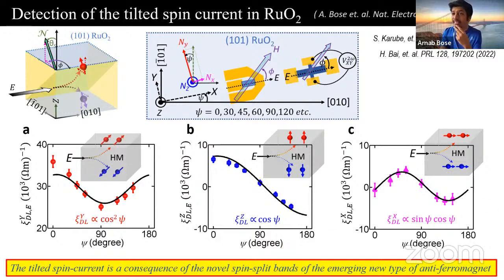We have also seen a couple of recent reports studying spin torques in this ruthenium dioxide, and particularly in this paper, they have reproduced our experimental observations. Previously there has also been a report of spin torques generated by another collinear antiferromagnet, manganese gold, but this work is completely different from that, because here we observed that the generated spins are polarized roughly along the direction of the Néel vector, unlike this case. So the antiferromagnetic spin Hall effect or the tilted spin current we are reporting here is fundamentally different from this.